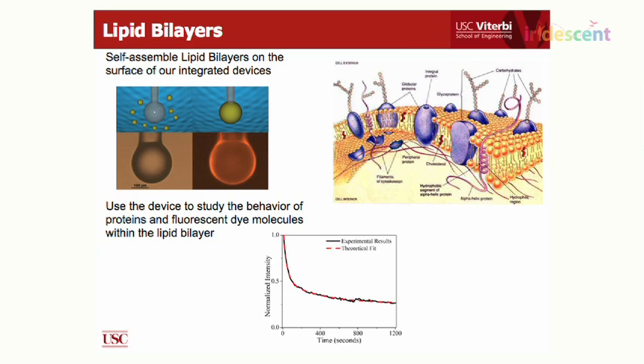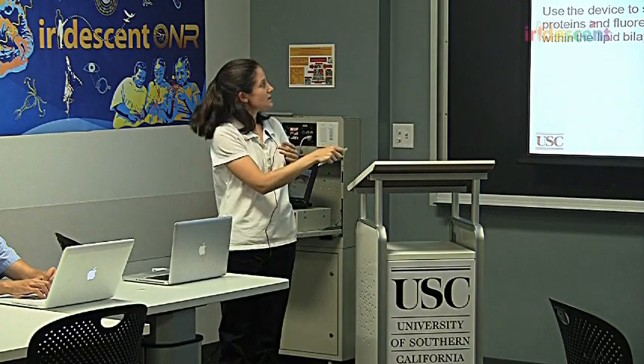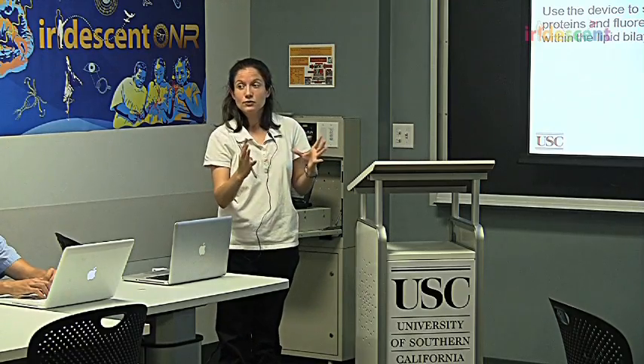This is an optical picture, not an SEM. So it's like the normal standard wide field picture, and this is a fluorescence picture. The reason why this picture is significant is because we actually put a fluorescent dye in the bilayer, and so we showed that we basically had this very nice uniform bilayer all over the surface of our resonator. So this is kind of nice, and it's a nice cute little optical trick.